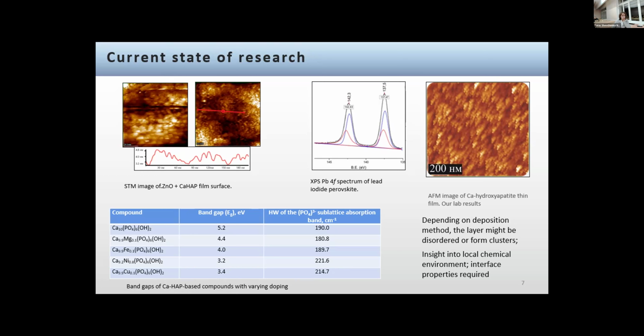Of course, in the XPS experiment it is very much exacerbated because it's exposed to the X-rays, not to the ambient solar light. And this is what allowed us to see this decomposition almost in real time. So from scan to scan, the single peaks that corresponded to the chemical bonds in the perovskite structure were splitting into double peaks firstly, that were interpreted as lead iodide molecules, and then further split into additional peaks that were interpreted as pure metallic lead. So this is how we observed this degradation almost in real time.